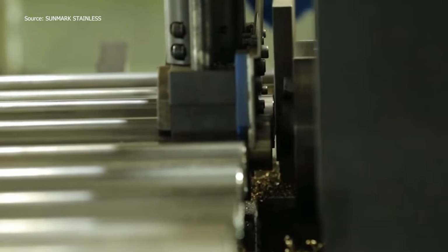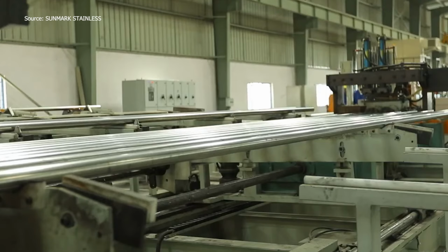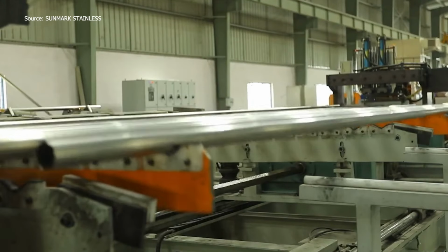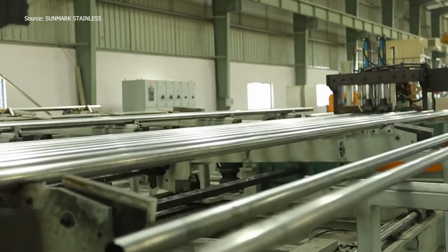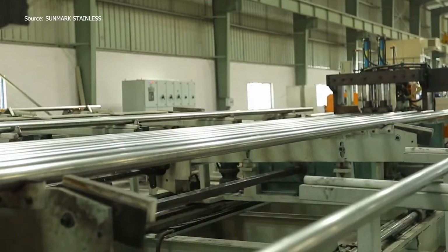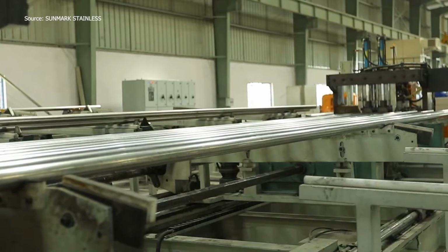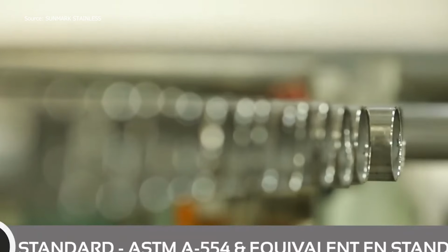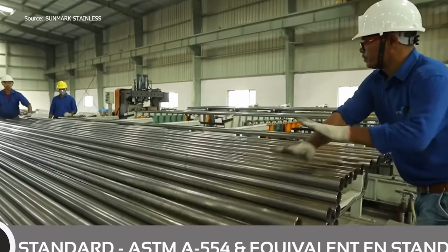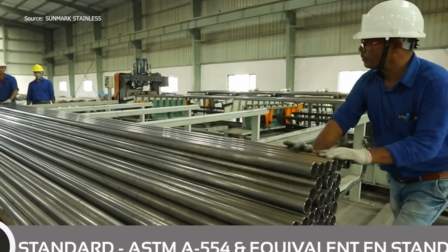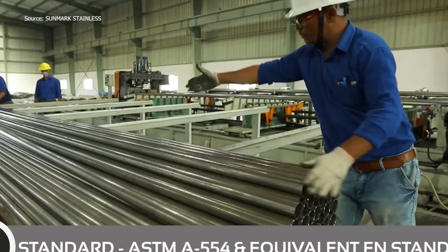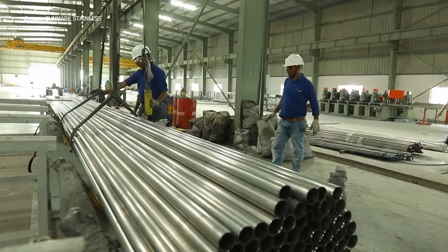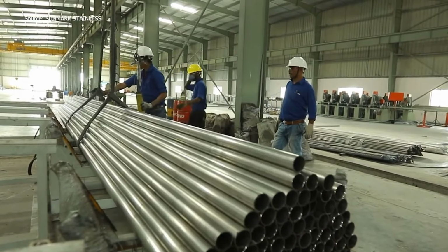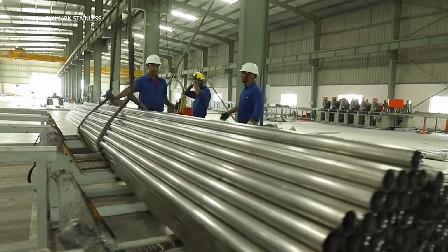Next comes finishing, a hallmark of Sunmark's stainless identity. Depending on customer requirements, surfaces are polished to 180 grit, 320 grit, 400 grit mirror, or even 600 grit mirror finish. Specialized polishing heads ensure a uniform grain direction and gloss level, giving the tubes not just shine, but measurable smoothness critical for their industrial and architectural use. That level of refinement gives the product its character, engineered, not embellished.